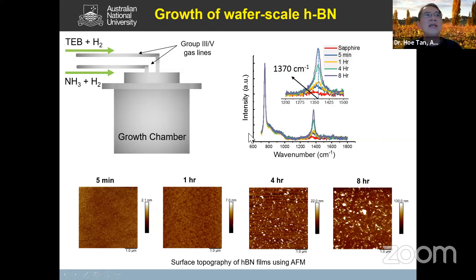And the way we do it is by using ammonia, which is the nitrogen source, and triethyl boron as the boron source. Okay, so we introduce these in the growth chamber, and boron nitride needs a very high growth temperature. So we typically grow this at about 1300 degrees Celsius. Okay. So as you can see here, 5 minutes growth, AFM image, 1 hour, 4 hour, 8 hour.